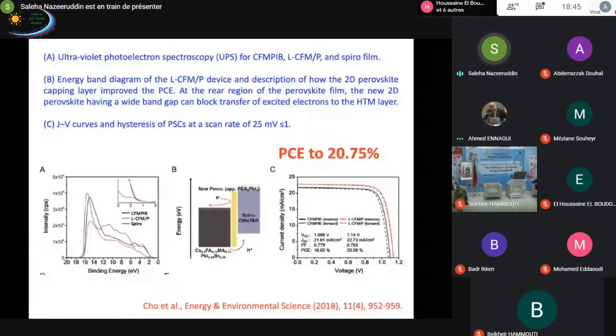While using the UPS measurement data, the middle panel, that's the energy level diagram, we extracted. So the take-home message from this slide is the energy level of three-dimensional perovskite, which is here the mixed cation, mixed halide perovskite, and the energy level of the two-dimensional perovskite, that's the yellow line. If you look at the HOMO level of the three-dimensional perovskite and then the two-dimensional perovskite, they are well aligned. However, if you look at the LUMO level of the three-dimensional perovskite and two-dimensional perovskite, it is extremely higher, similar to the hole transporting material.